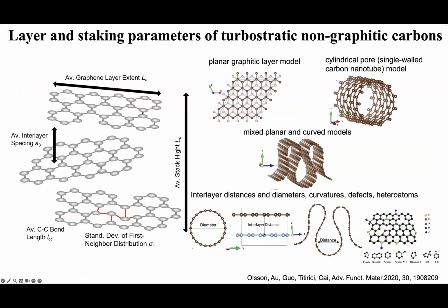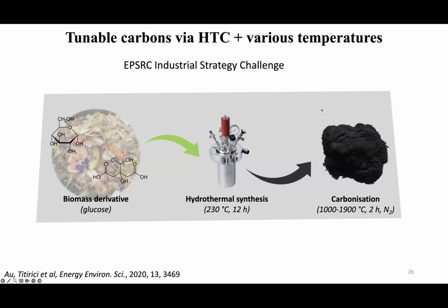Hard carbons are difficult. People believe the hard carbon is just one thing and you can take anything and burn it and you'll get a hard carbon. But in reality, maybe yes, that is true, but you really need to understand all these parameters, the interlayer spacing, the graphene layer extent, the average carbon bonds, the pores, whether they're closed and open, the crystallite sizes and so on, the defects, whether there are heteroatoms, hexagons, and pentagons, to really figure out the best hard carbon for sodium-ion batteries.